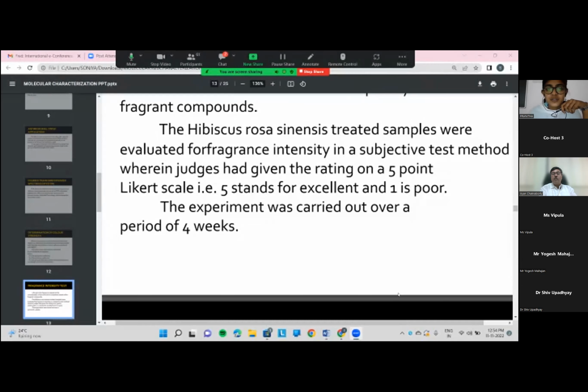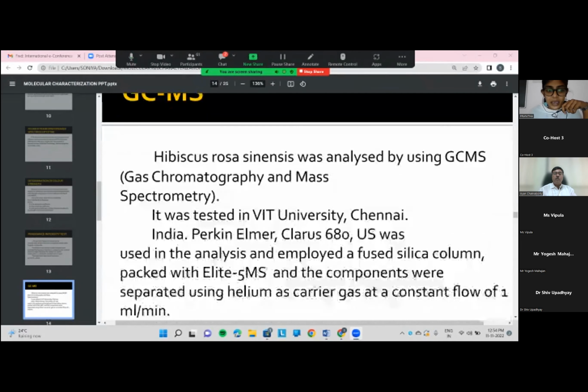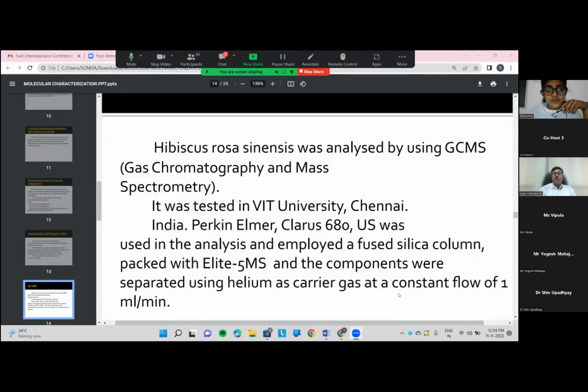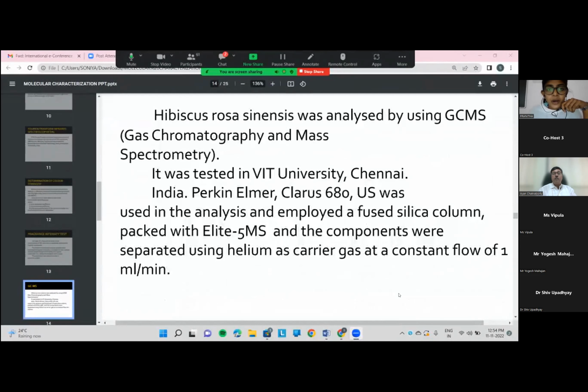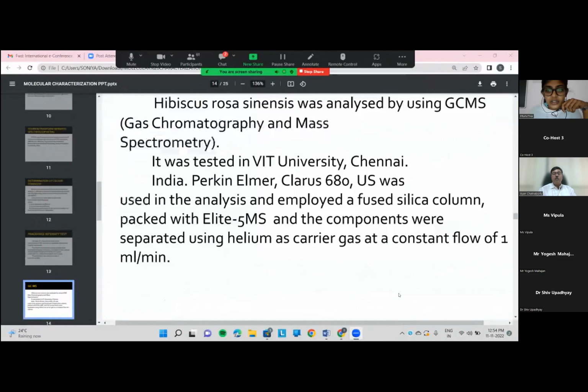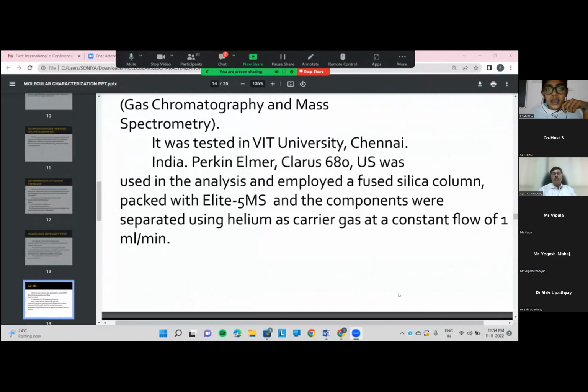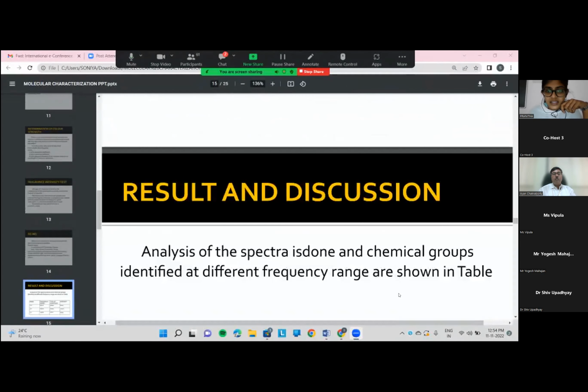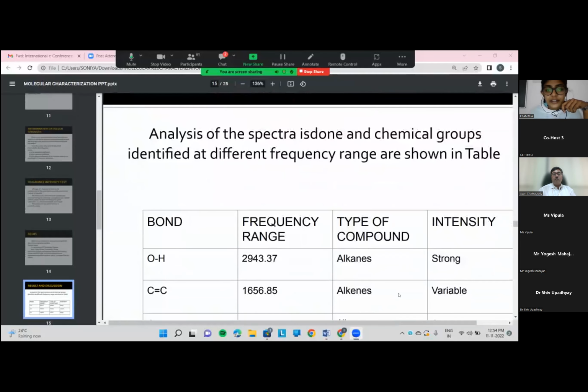GCMS. Hibiscus rosa-sinensis was analyzed using GCMS, gas chromatography and mass spectrometry. It was tested at VIT University, Chennai, India. A PerkinElmer Clarus 680 was used in the analysis and employed a fused silica column packed with Elite 5 MS, and the components were separated using helium as carrier gas at a constant flow of 1 ml per minute. Results and discussion. Analysis of the spectra is done and chemical groups identified at different frequency ranges are shown in the table.